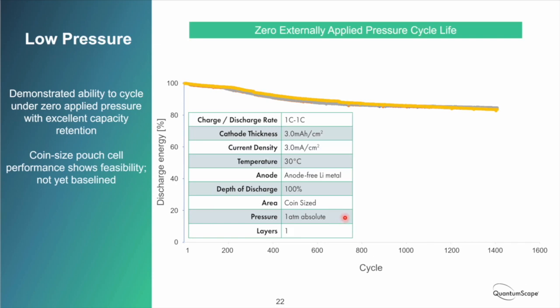So here were some small cells that we put on just as a feasibility test, showing cycling at 1C, 1C conditions, still relatively thick cathodes near room temperature with anode-free lithium metal, full depth of discharge. They were relatively small cells. We haven't baselined this in our large cells, but cycling at 1 atmosphere absolute pressure, meaning these pouch cells were unfixtured. There was nothing additional applying any pressure. They were just in a pouch cell that we evacuate. So you get ambient room pressure on the outside of the pouch cell. So 1 atmosphere absolute pressure.